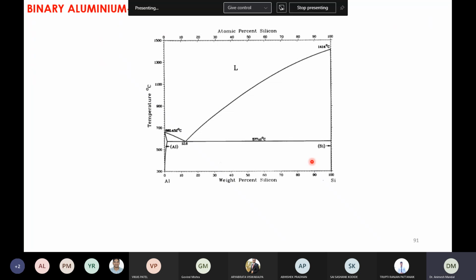And this is a very serious problem in many aluminum castings. Foundries still report this, because the understanding behind it was quite limited, and not many techniques were there to see how this cracking occurs during solidification. It's very difficult when anything is happening in the liquid or semi-solid state, so it becomes difficult for science to understand. But with more modern equipment, we now understand the reasons for hot tearing in different kinds of alloys, and more or less the issue has been solved, though a lot of studies are still going on even in aluminum copper alloys. So what can be done to overcome this hot tearing issue? Because once you get hot tearing, that component is simply rejected.